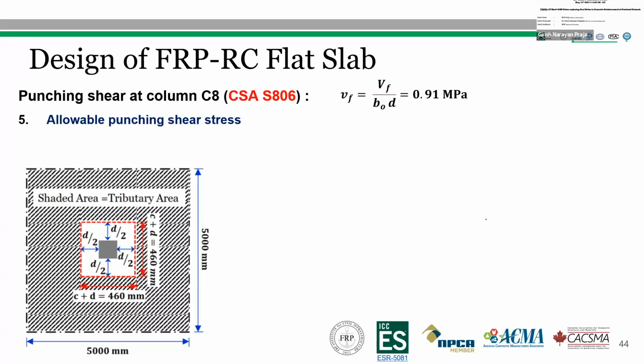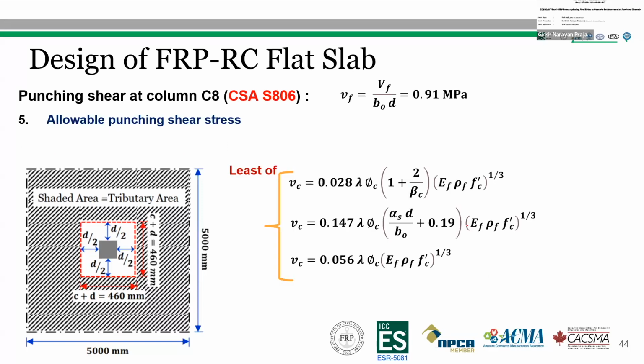So as we calculated before, the ultimate factored shear stress is 0.91 megapascal, and the allowable punching shear is the least of these three equations according to the Canadian standard CSA S806. And the variables in the equations are alpha S, which is the column location factor, and is 4 for interior columns, 3 for edge columns, and 2 for corner columns. So for the present case, alpha S is equal to 4, and beta C is the ratio between the long side to the short side of the column and is equal to 1. And E_F is the modulus of elasticity and is equal to 65 gigapascal. Rho F is the reinforcement ratio from design, and lambda is the factor to account for the concrete density. And for normal strength concrete, lambda is equal to 1. And phi C is the resistance factor for concrete.